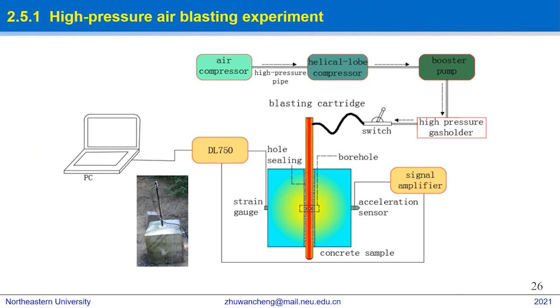This slide shows the experimental setup for high-pressure air blasting on concrete specimen. Through air compressor and booster pump, the air, atmosphere, is compressed to a maximum pressure of 100 MPa and then stored in high-pressure gas holder. The uniaxial compressive strength of the concrete samples is about 20 MPa. High-pressure air of 40 MPa is used in the experiments.